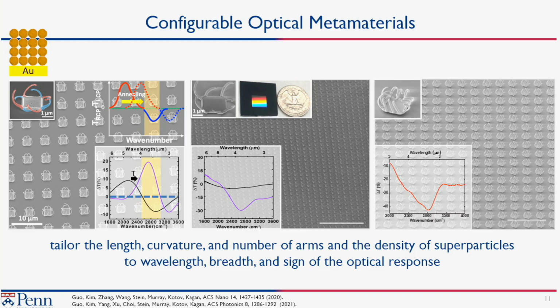So we would make these structures. We made ones with different numbers of arms, different lengths of arms to try and make broadband chiral materials, which we did over time. But one of the questions we often got was, well, with nanocrystals, could you make them reconfigurable? And we would have loved to, but we really formed good bonds. As much as we could swap ligands out, once we form a good bond like that, we weren't going backwards.